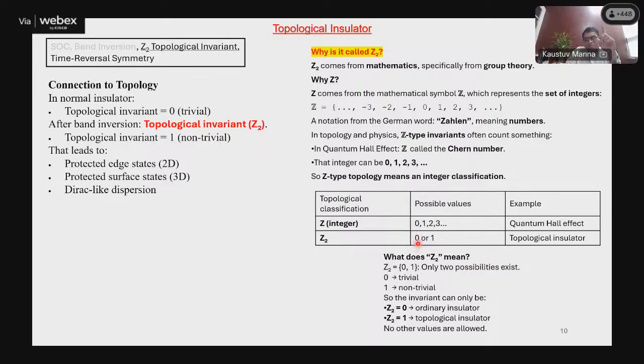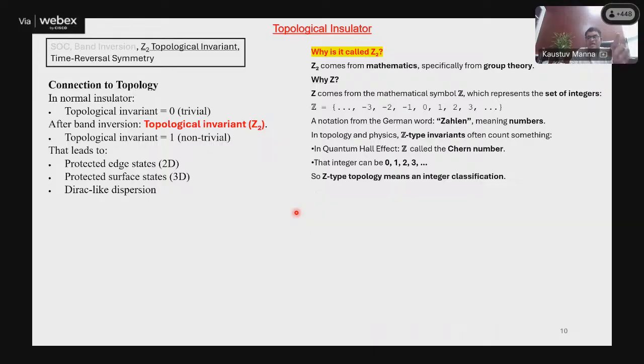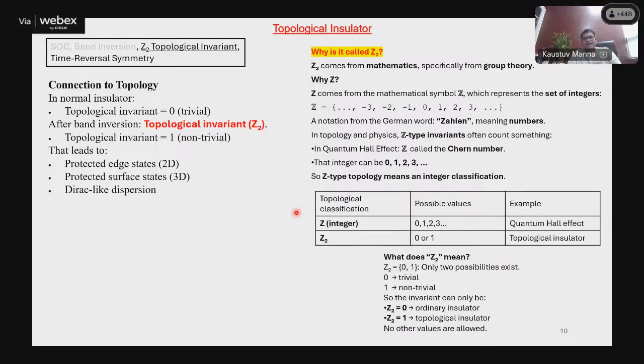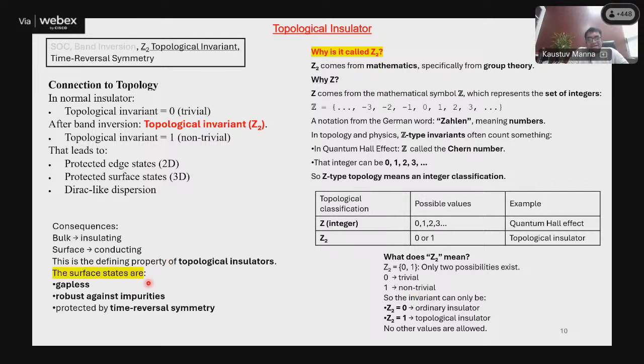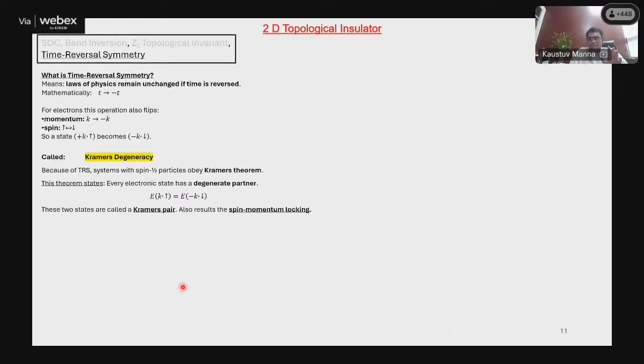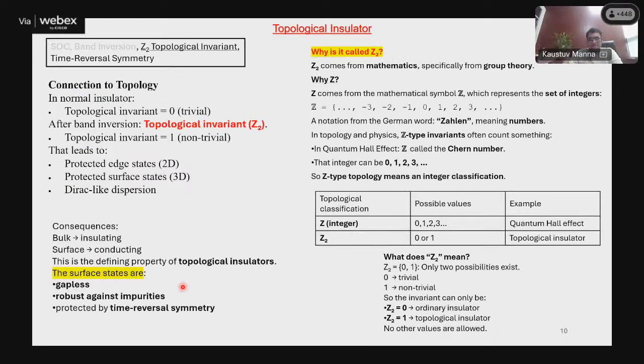So what does 0 represent in this Z2? 0 represents the trivial state. That means the bulk is already gapped because of the SOC. As in the previous slide, I have shown that the bulk is gapped. That means Z2 equal to 0 is satisfied. Z2 equal to 1 means a non-trivial state, the edge state. What is the edge state? The edge state is the gapless state at the edge of the material. And how does it appear? Sorry, in the next slide I'll show how the edge state appears because of the band inversion. Everything is connected.